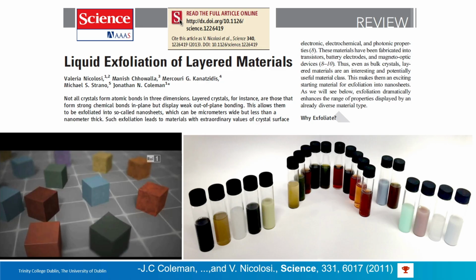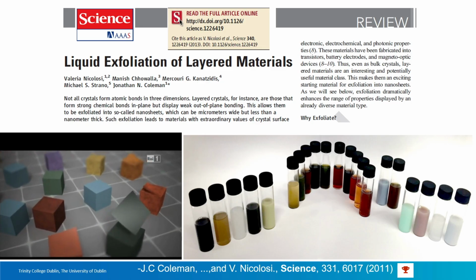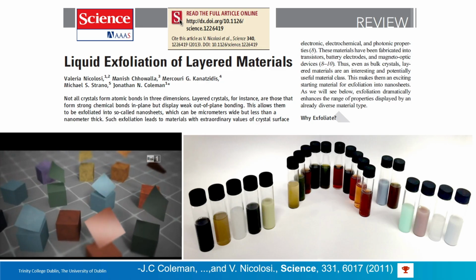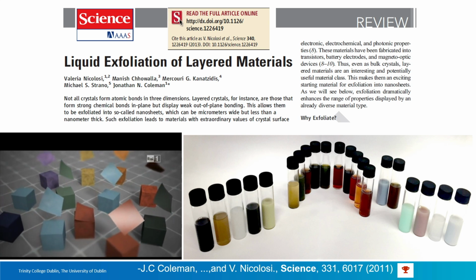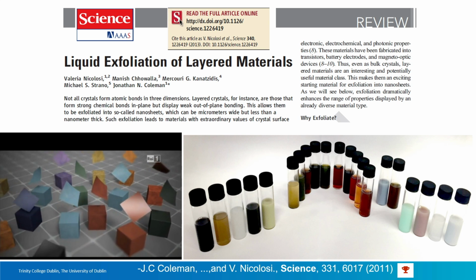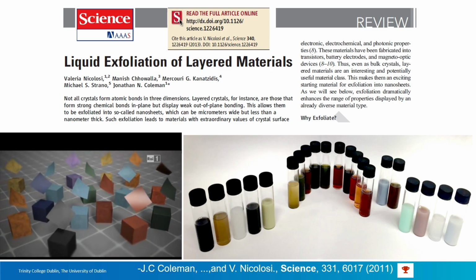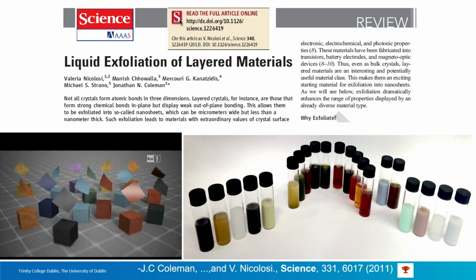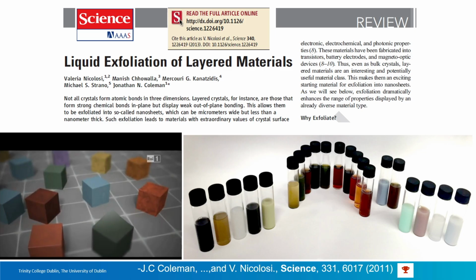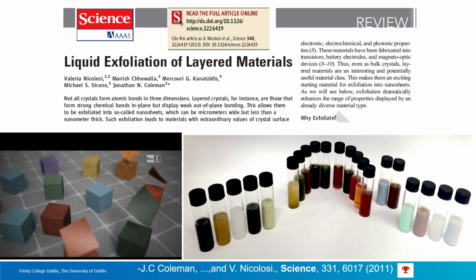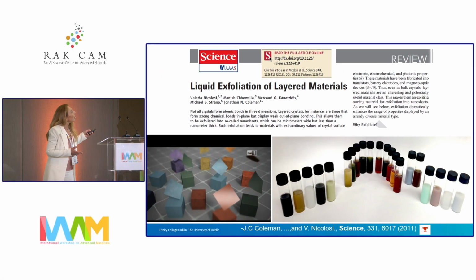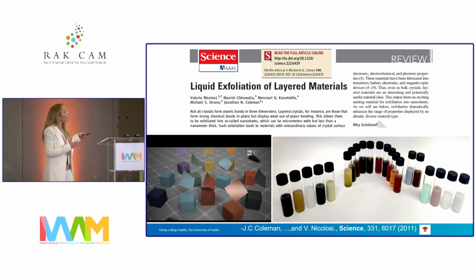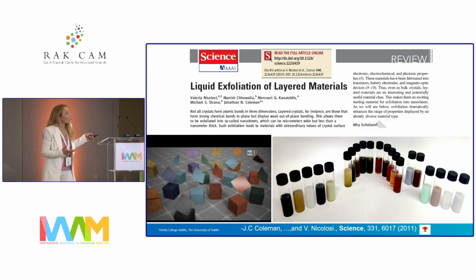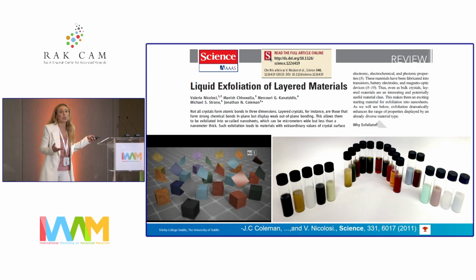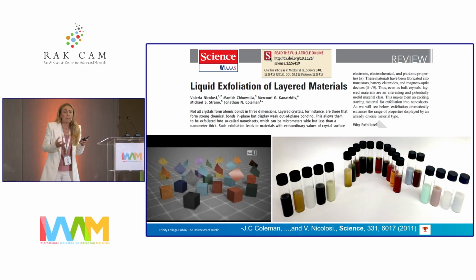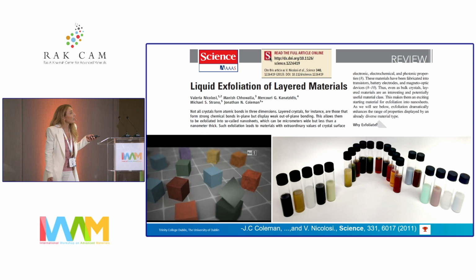We moved very recently, after applying this method to graphene, to really apply the same liquid phase exfoliation methodology to hundreds of other layered crystals in nature. Transition metal oxides, chalcogenides, and so on. The method is pretty much the same. And this snapshot shows the variety of different materials we can exfoliate.